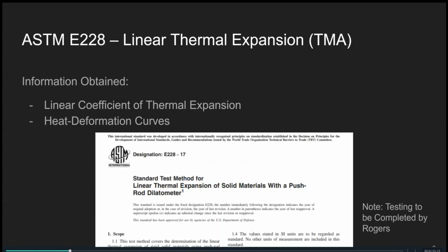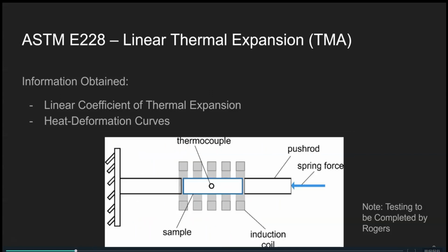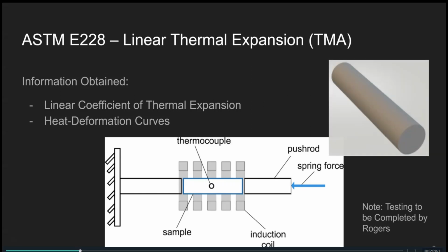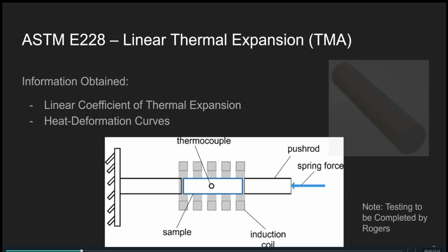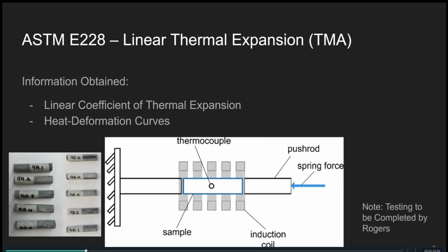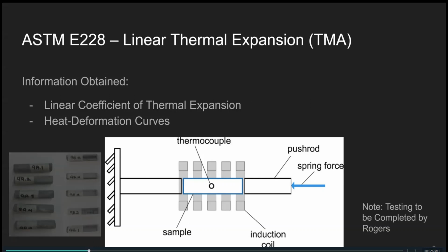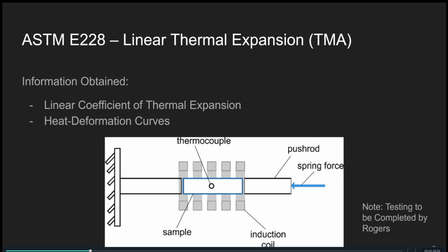So the first test I'll go over is ASTM E228, which is linear thermal expansion. We contracted this out to Rogers, who used a thermomechanical analyzer to measure the deflection of a workpiece when exposed to a temperature range, which was metered by a thermocouple. So this helped us determine the linear coefficient of thermal expansion and capture heat deformation curves to see how the material would react under high temperature loads, seeing the deflection and stress induced by those processes.